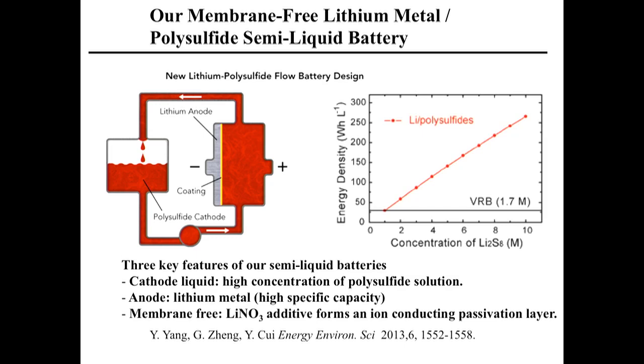It's the best. So that's right here. You can get to 10 molar solubility for the polysulfide. Well, this is vanadium redox flow, 1.7 molar. Now you see right away, if you have 1.7, I can get to 10. I have 5 times, 6 times more solubility. My energy density will increase 5 to 6 times more. If I do the same amount of investment on the pumping and piping and big tank, my cost per energy is reduced by 6 times, right?